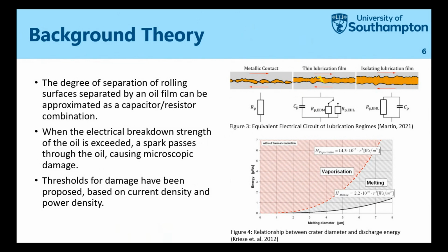When the charge across the contacts exceeds the breakdown strength of the oil, you get a spark discharge through the oil, allowing the voltage to pass through the contact, which can, in severe cases, cause microscopic damage to the bearing raceway, which is what causes it to fail faster.